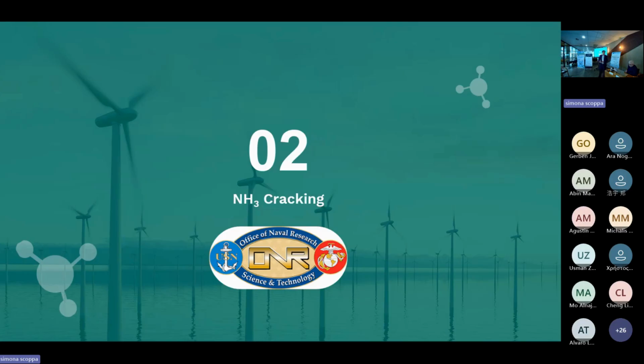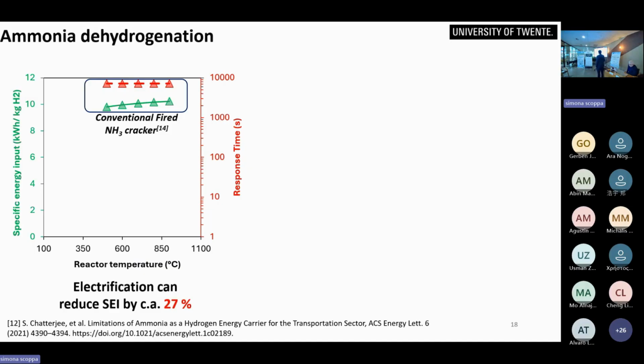They came to us with a very specific question: can we do ammonia cracking? And we came up with a few ideas, and they selected this, which is called dynamic catalytic cracking. And the idea here is that if you have a conventional fired ammonia cracker, this is not my data, so please, colleagues in the audience, forgive me, this is not right. You get these kinds of specific energy inputs in the order of 10 kilowatt hour per kilogram of hydrogen. And in principle, if you get rid of the very high temperatures that you need for these processes, this is at 800, 900 degrees C, you could lower the overall heat losses in the system by about 27%. So these are not my estimation. This is just from that paper that you see.